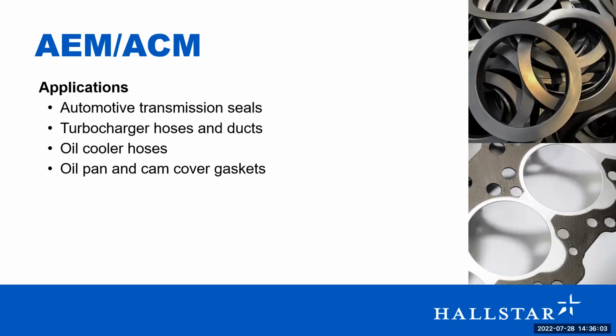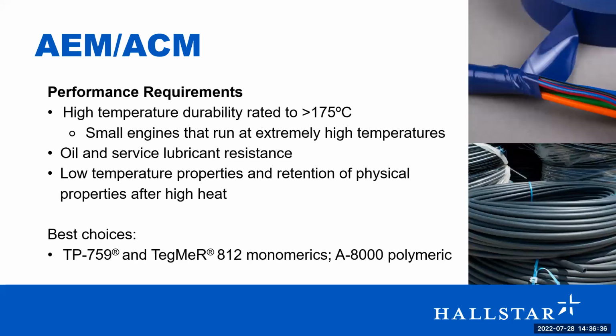So for AEM and ACM, a lot of the applications we see are the ones requiring even higher heat than HNBR. So these are going to be automotive transmission seals, turbochargers, hoses and ducts, oil cooler hoses, oil pan, and cam cover gaskets. So really, these are going to have to have very high oil, heat, and flame resistance, and a really high temperature range. So you're going to have to be able to pair up a plasticizer that would match with this. With some of these acrylic elastomers having to get over 175 Celsius, while a lot of polyester plasticizers and plasticizers in general will be compatible with this polymer system, there are very few plasticizers that are going to be able to maintain this temperature rating.